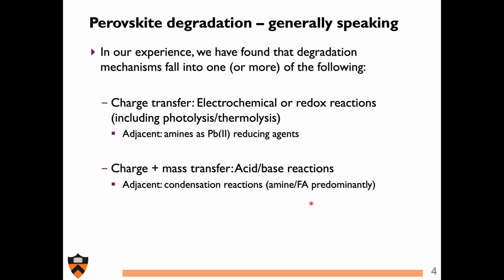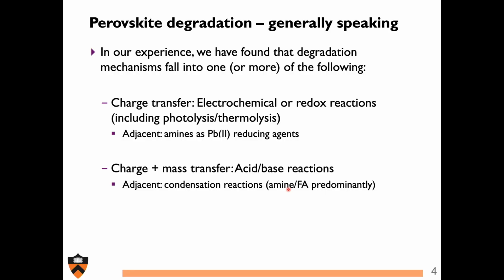The other thing that can happen with amines, and this is another adjacency, is a condensation reaction between amines and formamidinium, which also spells a lot of problems for this system structurally, because I end up making cations, the most common one is methyl formamidinium, that are just too big to fit in that perovskite lattice, and it kind of unfolds that system, leads to substantial strain and other things. But things like strain, things like ion migration, I like to think about them as consequences of one of these two things. And so these are kind of the original sin, as it were, for halide perovskite degradation.